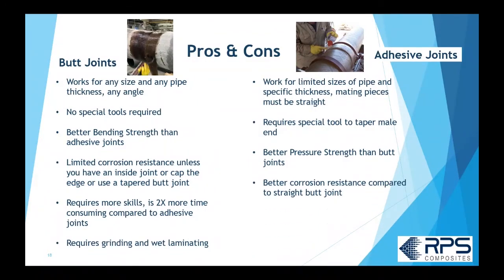And you also have better corrosion resistance with an adhesive joint, a tapered adhesive joint, because you can see it's pretty much a continuous corrosion barrier. Only that thin amount of adhesive is exposed, unlike the crevice paste where you have an abrupt amount of crevice paste there. And generally speaking, it's less steps in the adhesive joint. They're all very critical steps, but it's going to take about half the labor of the butt wrap joint. And with the adhesive joint, there's very little dust and there's less chemicals used. It's just the pre-mixed resin and BPO catalyst. Pour all of one into the other and you're done. So not a lot of fussing with chemicals.